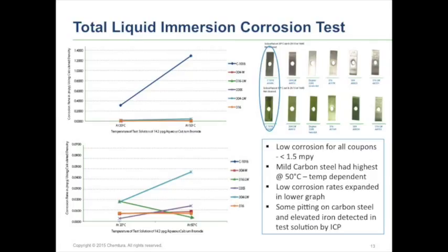The corrosion studies we did working with EPRI were focused more on the handling equipment, handling calcium bromide, and what you would need to do as far as introducing it into the system. We did 90-day tests. We did look at welds. We looked at basically carbon steel, stainless steel, and some duplex. And then we looked as well at just liquid submersion, just vapor, and then a mixture to see if you get anything involved with the surface. And again, this is all based on materials and construction for the right application here.